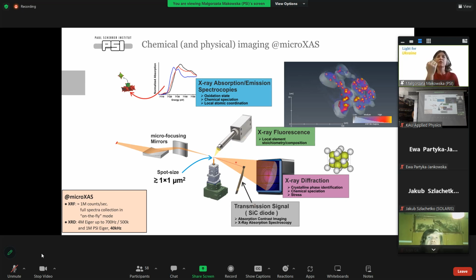And of course, another type of measurement that we used to do as a standard measurement was absorption spectroscopy, XANES or XAFS. But this, of course, had to be done with an energy scan, so not simultaneously with the others. But it could be done on the same sample after selecting a specific point, for instance, based on diffraction and fluorescence images.